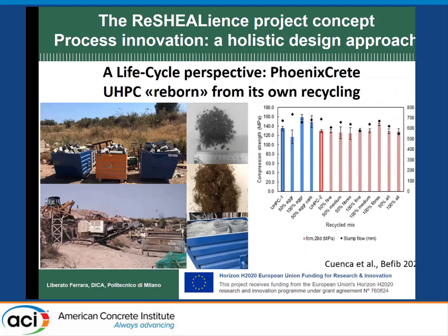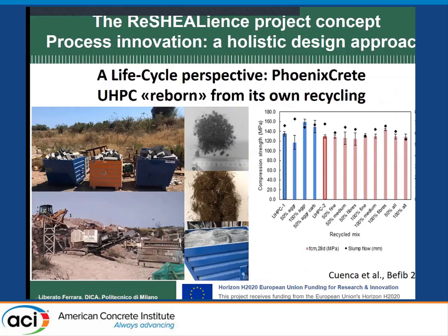But also, we have started a pilot study in order to bring these materials to a new life. So we crushed the specimens from our lab investigation, and we used them to produce a new UHPC, and you can see the results. These were obtained by 2 labs, University of Malta and University of Valencia, blue in Malta and red in Valencia, the columns. And you can see that with respect to the reference, whether you replace 50 or 100% of aggregates, or of aggregates and fibers in different fractions, you really are able to keep the performance.